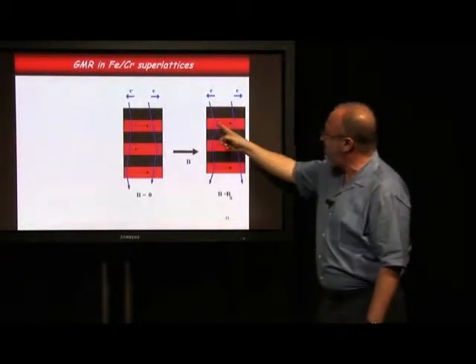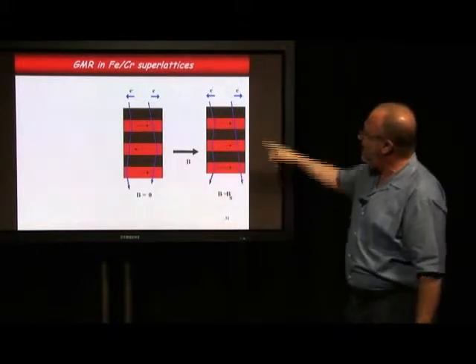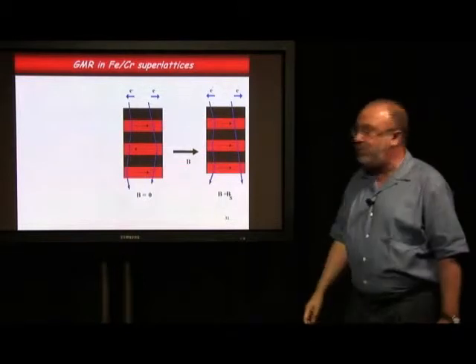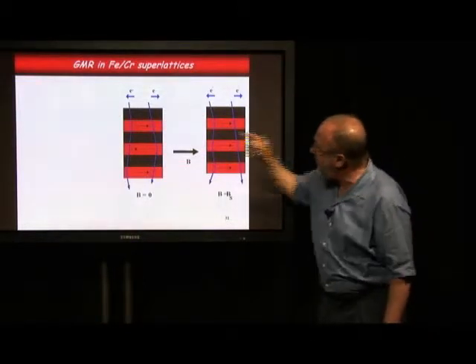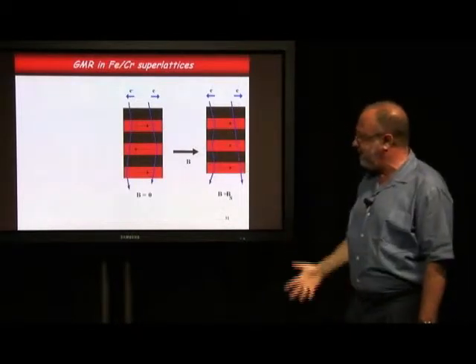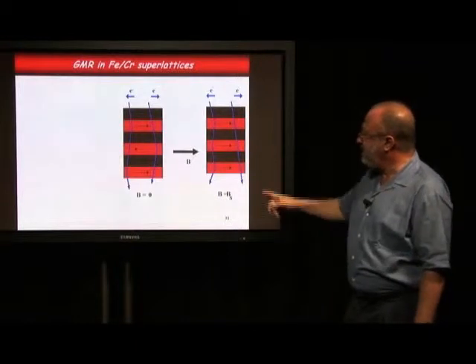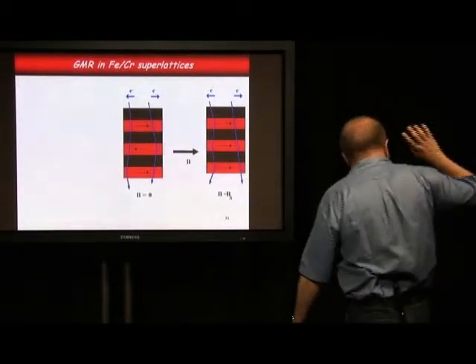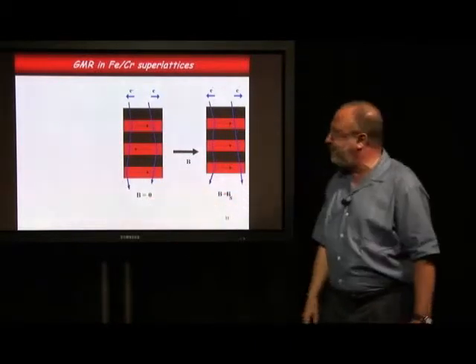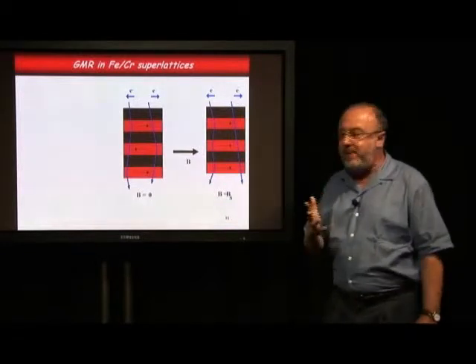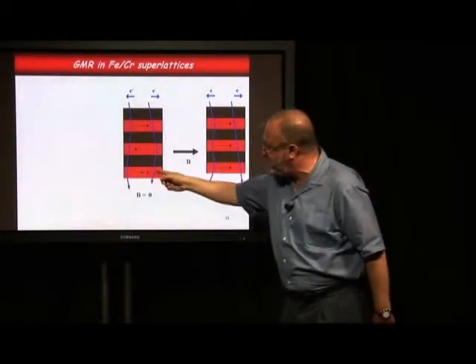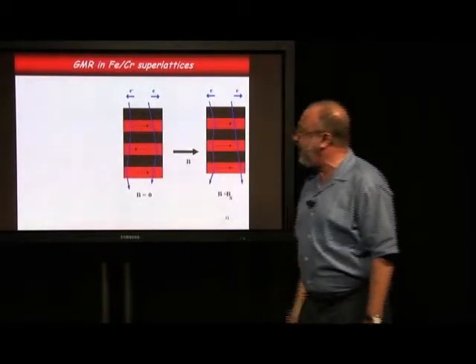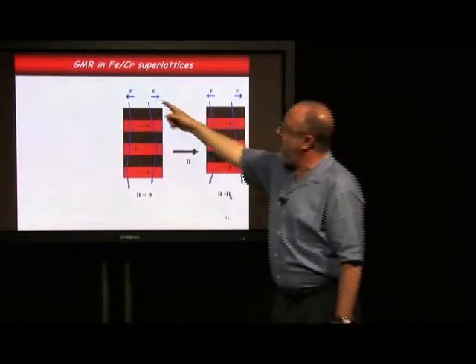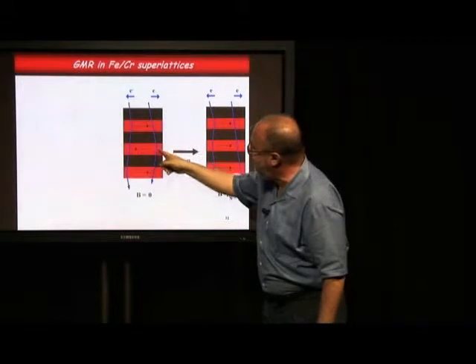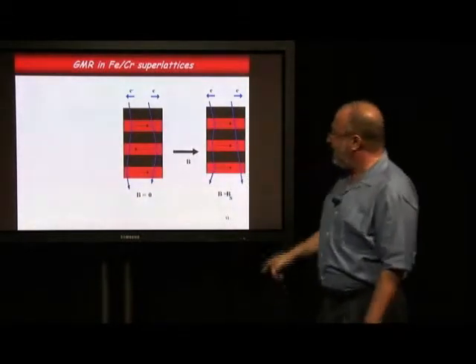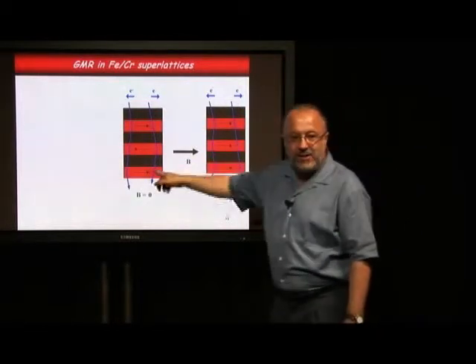It turns out that if all the magnetic moments point in the same direction, then the electrons pointing to the right are able to go through easily. However, the ones pointing to the left bounce against these red spins of the material that are pointing in the wrong direction. This is the situation in a high magnetic field pointing towards the right. In a zero or low magnetic field, these materials have this strange property that they order in antiferromagnetic layers. So the spin in one layer points to the right, the next points to the left, the next to the right. In this case, whether you have electrons pointing to the right or to the left, they both bounce. One bounces against this layer, the other against that layer. As a consequence, the resistance is high in one case and low in the other.